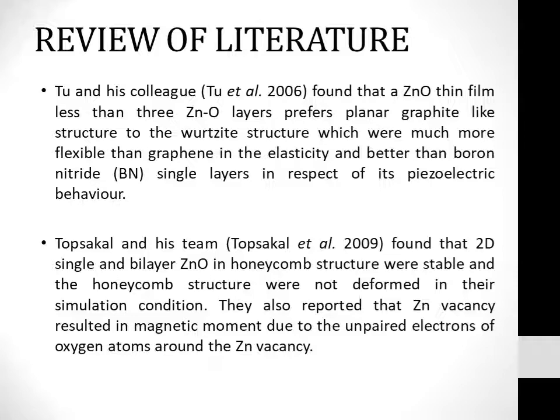Topsakal and his team in 2009 also found that the single layer of ZnO and bilayer of ZnO in honeycomb structure were in fact quite stable, and the honeycomb structure was not deformed in their simulation condition. They also reported that zinc vacancy resulted in magnetic moment due to the unpaired electrons of oxygen atoms around the Zn vacancy.